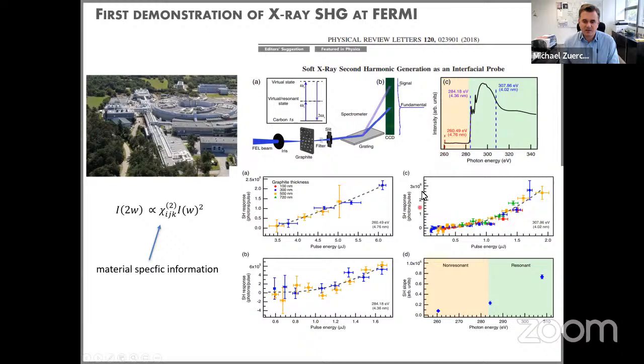And then what you typically first do is you look at the second order response. So basically you're counting the second harmonic photons depending on the pulse energy of each individual laser pulse impinging on the target. And the first thing that assures you that you actually look at a second order process is that you see this quadratic response here nicely. And so that is the first indication you have, yes, indeed, that's second harmonic generation on that system. So that is great. So now what is the actual observable? What are we interested in measuring?